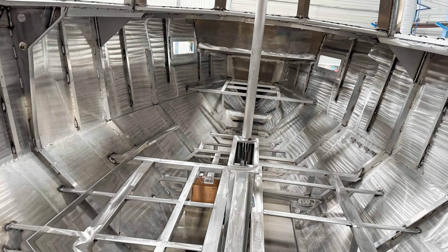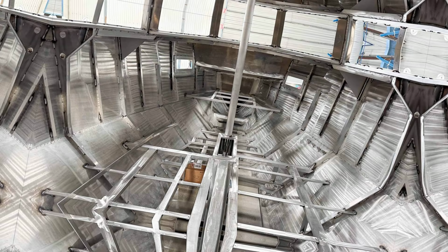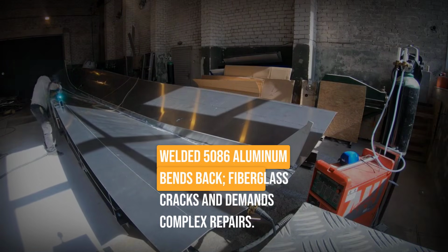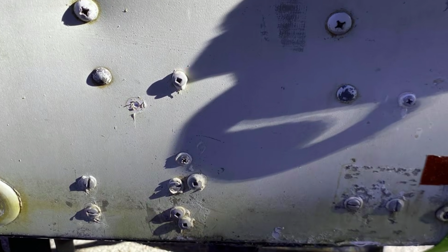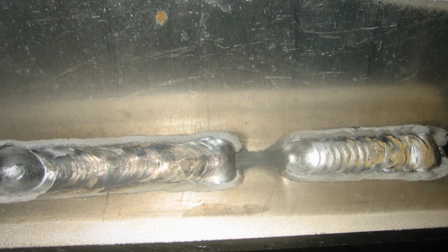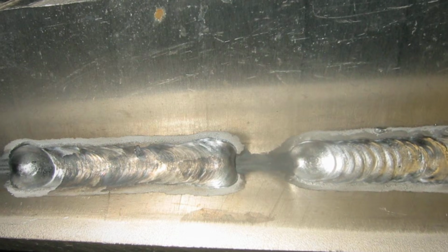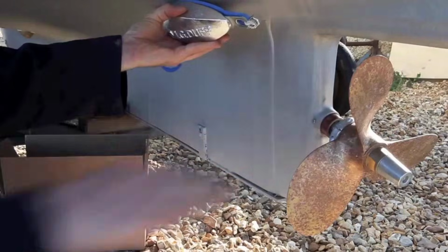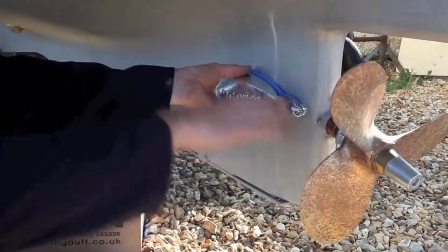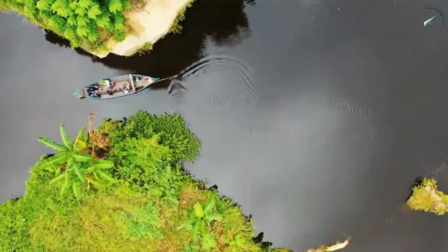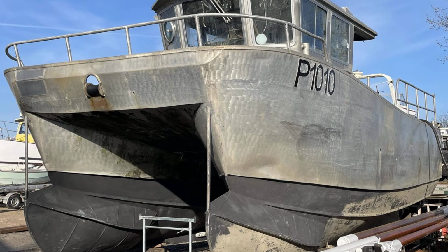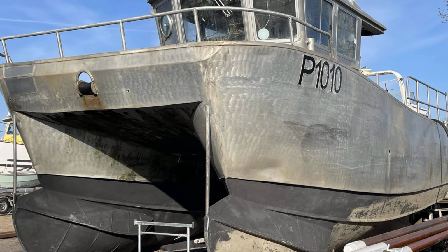The longevity equation also depends on the construction method. Welded aluminum hulls are structurally superior to riveted ones. Riveted hulls allow water infiltration between the rivet and hull material over time, particularly when the alloy used is not true marine grade. A well-built welded hull in 5086 aluminum, properly protected with anodes and barrier paint, can outlast a comparable fiberglass hull in freshwater or mixed environments by a significant margin. In the most abusive operating conditions, aluminum wins.